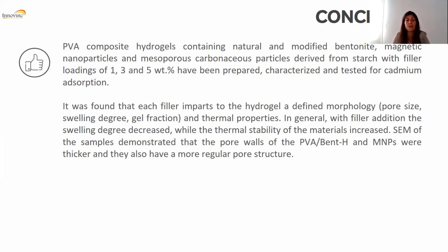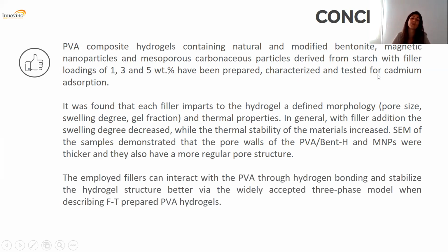SEM of the samples demonstrated that the pore walls of the PVA, acid-resistant bentonite and magnetic nanoparticles were thicker, and they also have a more regular pore structure. The employed fillers can interact with the PVA through hydrogen bonding and stabilize the hydrogel structure, via the widely accepted three-phase model when describing the freezing-thawing prepared PVA hydrogels.